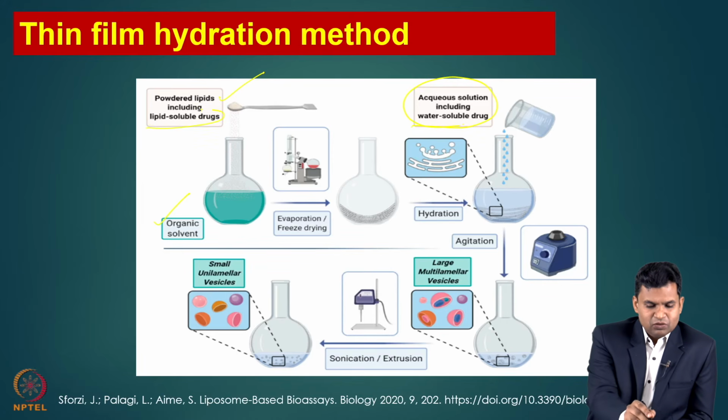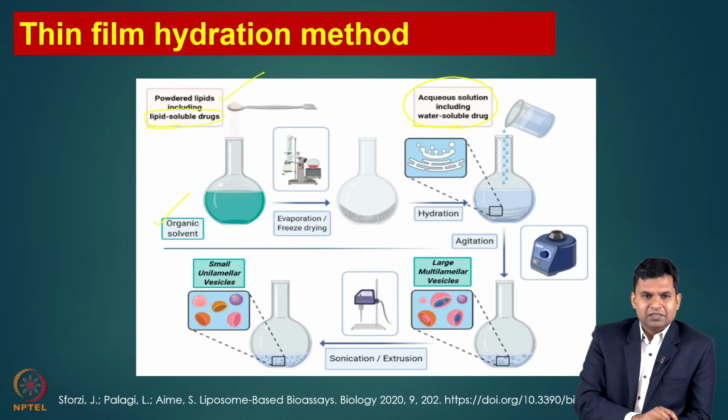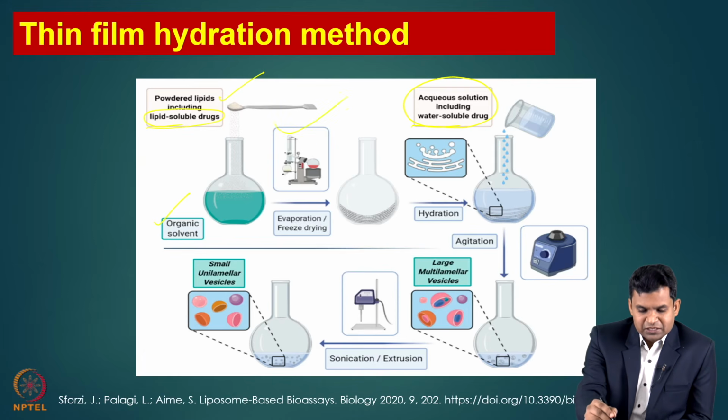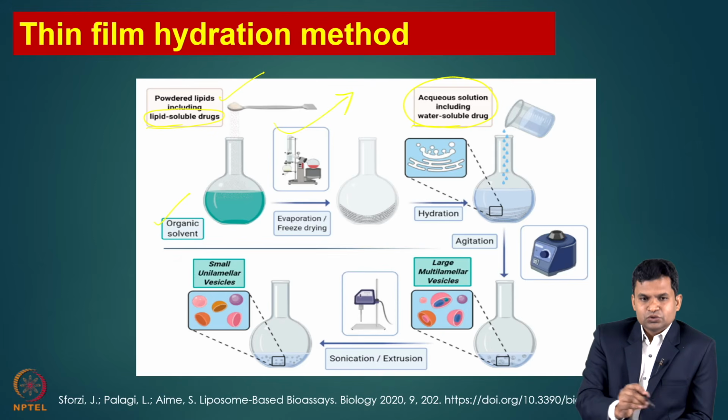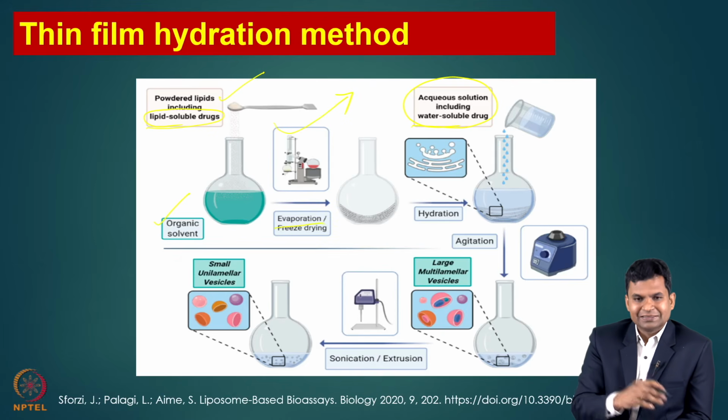If a drug is water insoluble or lipophilic, lipid soluble, you can disperse it in stage 1. Once you dissolve your lipid and the drug, you need to remove the solvent, which you can do by the evaporation technique or other techniques.